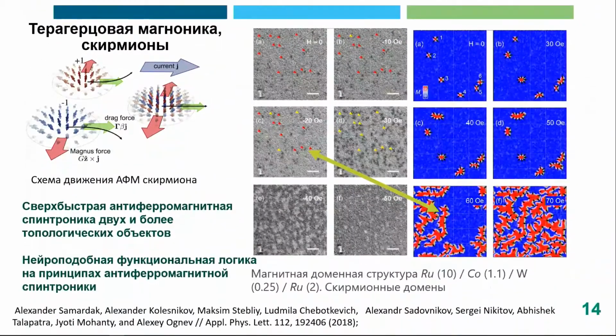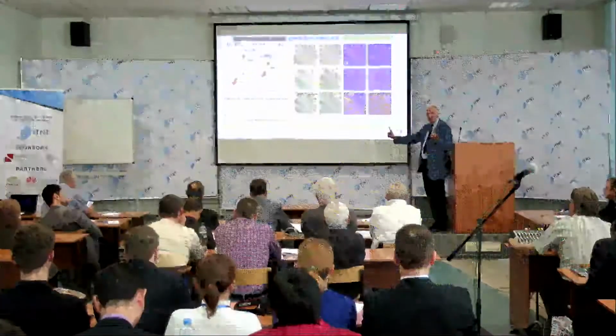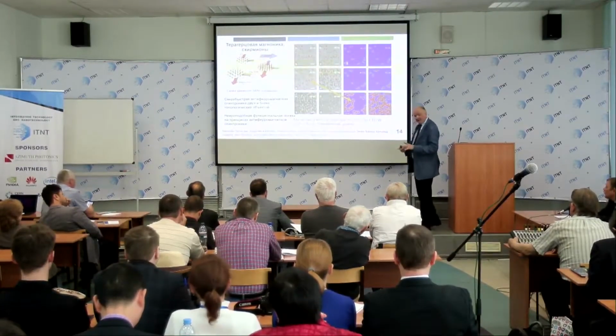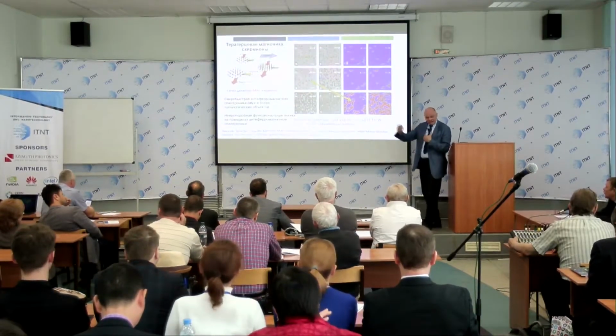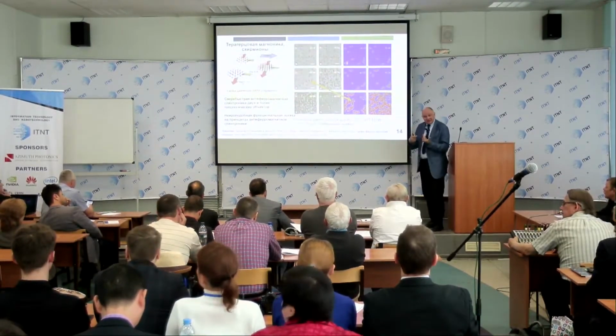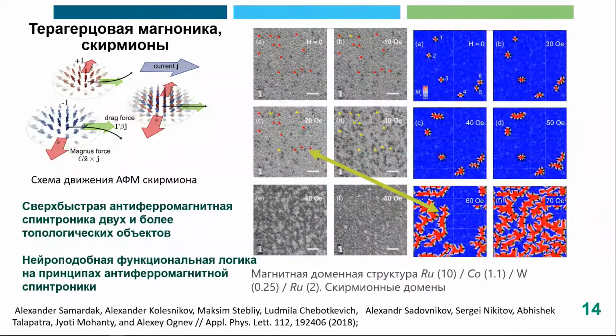Excitation of these skyrmions is very strong in antiferromagnetic materials. What is the difference between ferromagnetic materials and antiferromagnetic materials? In a ferromagnetic material, if you put it into an external magnetic field, then all magnetic moments are directed along this magnetic field. It has one magnetic lattice, we would say. However, there are magnetic materials where you have two sublattices. A very simple example: when you have two sublattices and their directions of magnetization are opposite to each other, then the total magnetization can be equal to zero. However, this material is a magnetic material, but the total magnetization is different.